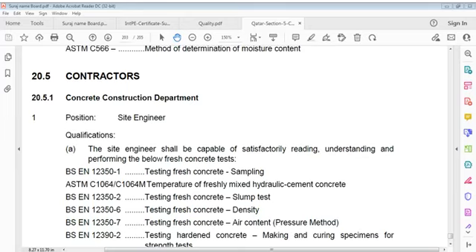Overheating of concrete is objectionable because it may accelerate chemical action, cause excessive loss of slump, and increase water requirement for a given slump. Moreover, warmer concrete as placed has a greater drop to ultimate low temperature, with corresponding increase in thermal shrinkage.